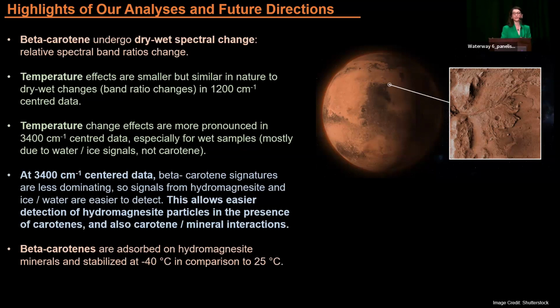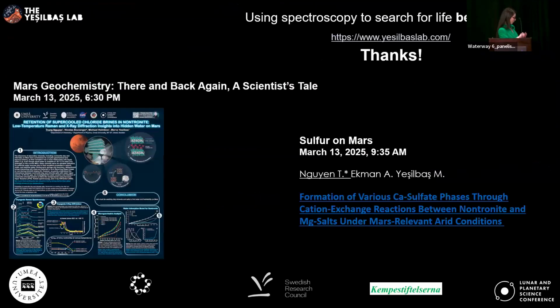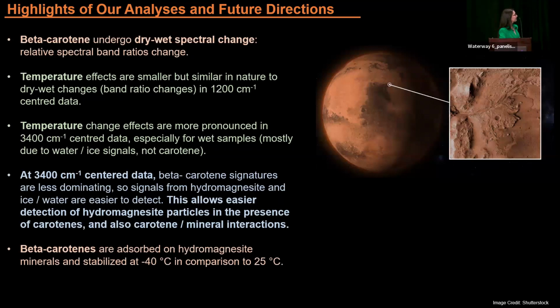But now we know that beta-carotene is the one that shows a lot of dry-wet spectral change responses, and is also minorly affected by temperature. But most importantly, which was also interesting, beta carotenes are absorbed on hydromagnesite minerals and stabilize there at -40. I have tried at -10. It was not like that. So just a peek.